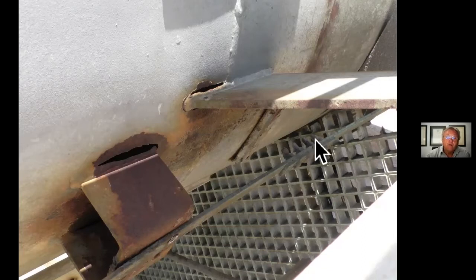However, what happened here is that the cooling effect of these sections that were then welded onto the shell of this chimney caused those areas to be cooler than the rest of the structure, and therefore you got dew point conditions on the inside of the stack at these points. And when you look at the stack from the inside, you wonder that it actually was still standing at the time that they took it down.